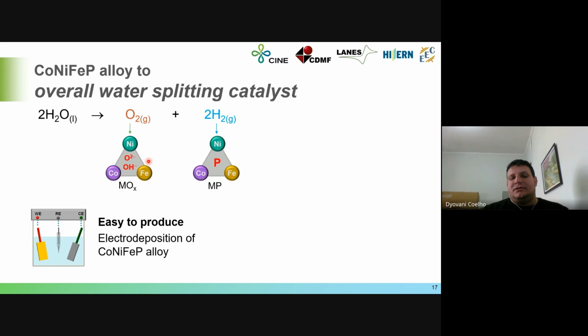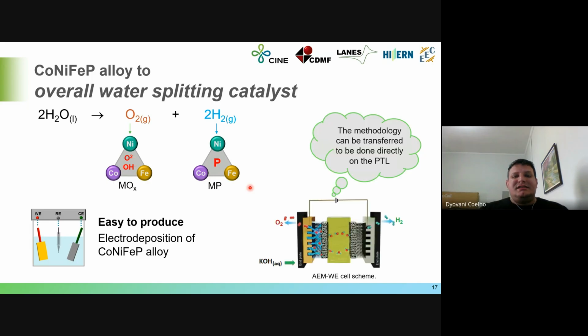But for the hydrogen evolution reaction, theoretically, this metallic phosphide can be stable during the reaction, but we can see what is happening. And that kind of catalyst can be produced really easily, just by electrodeposition. So this was the main goal: use something that is easy to produce, so that this technology can be transferred to be done directly on the porous transport layer, exactly like the chain made with nickel iron in the previous slides that I showed you.